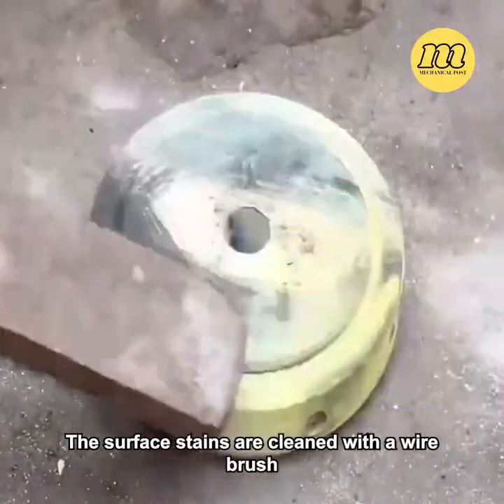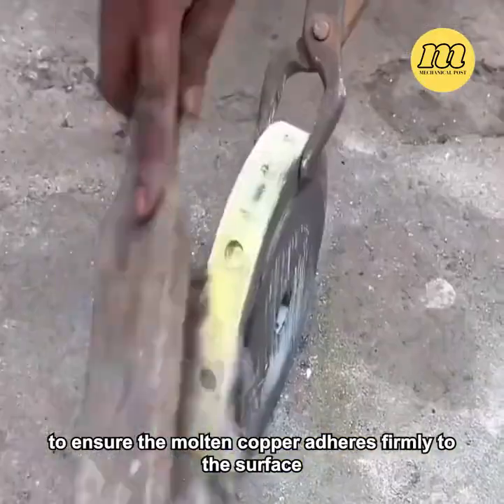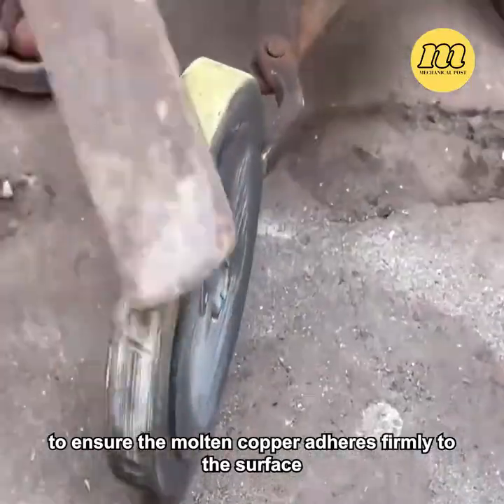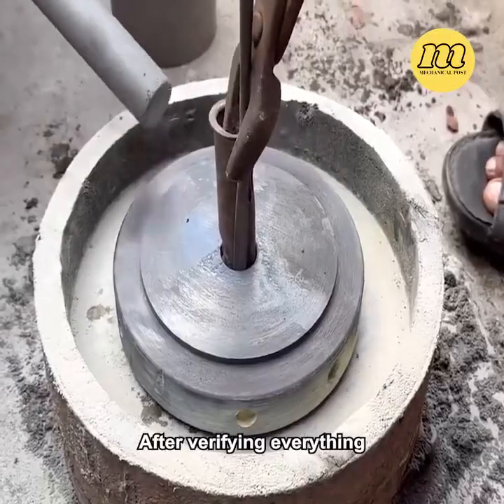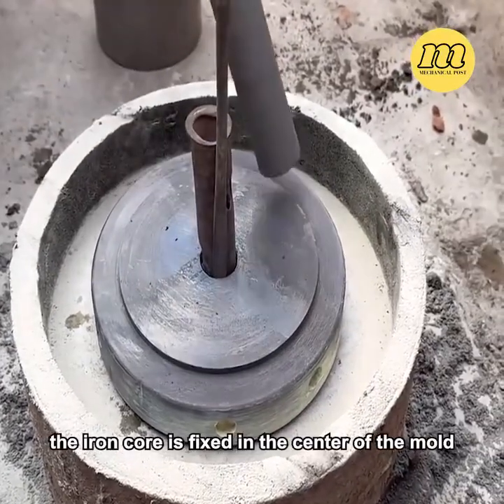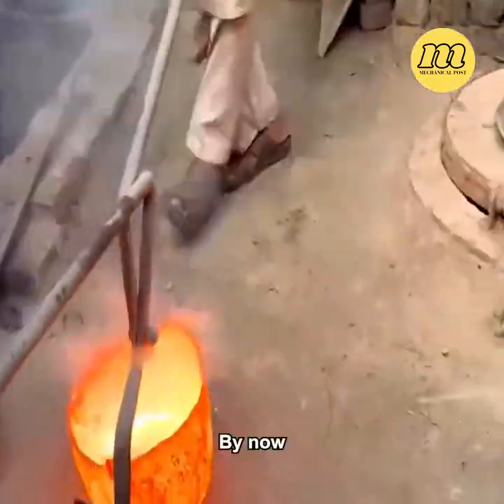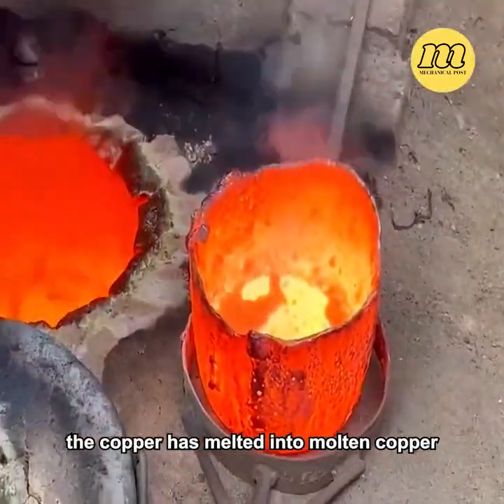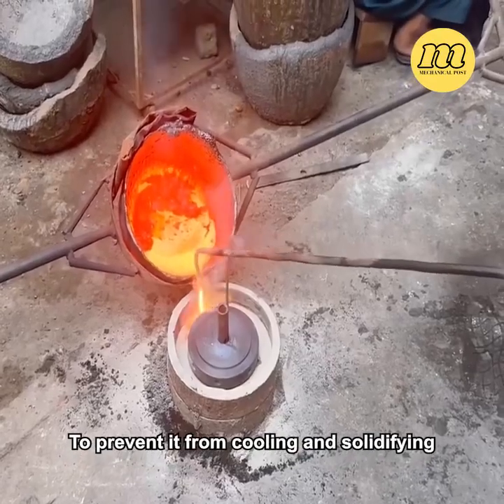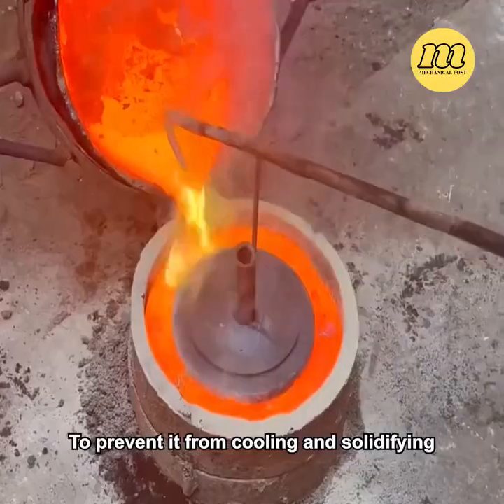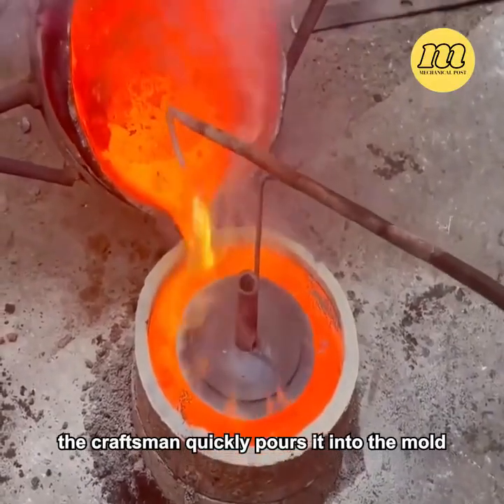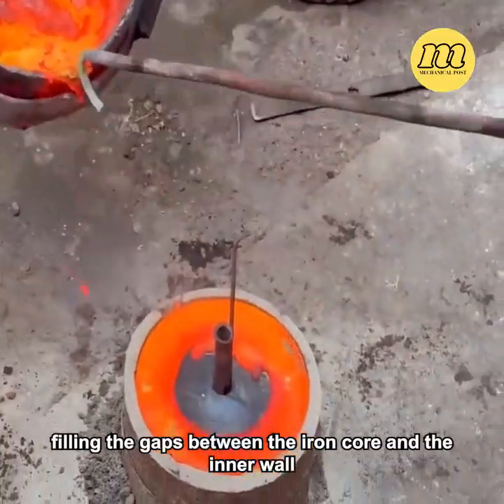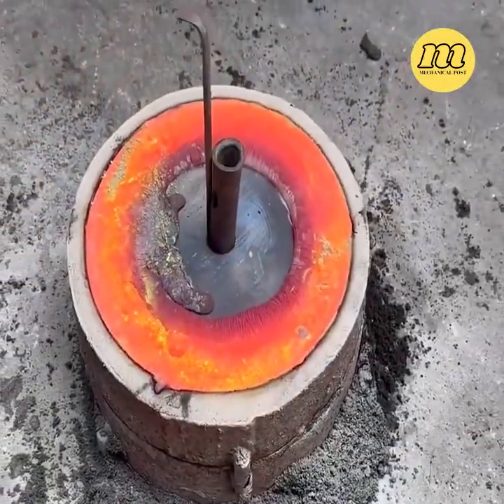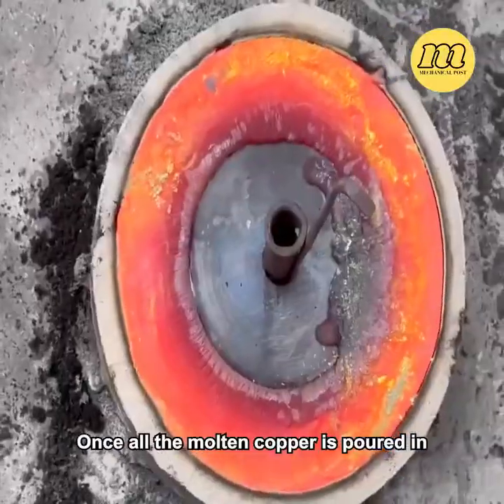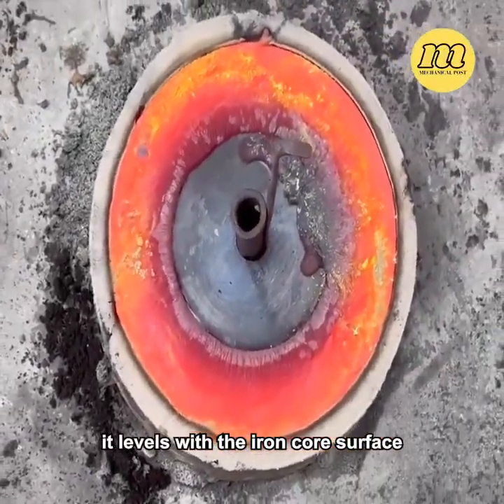The surface stains are cleaned with a wire brush to ensure the molten copper adheres firmly to the surface. After verifying everything, the iron core is fixed in the center of the mold. By now, the copper has melted into molten copper. To prevent it from cooling and solidifying, the craftsman quickly pours it into the mold, filling the gaps between the iron core and the inner wall.